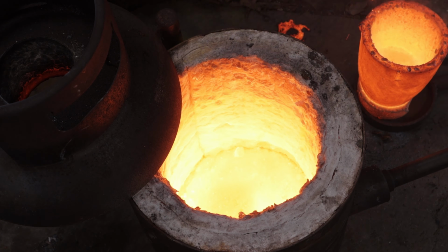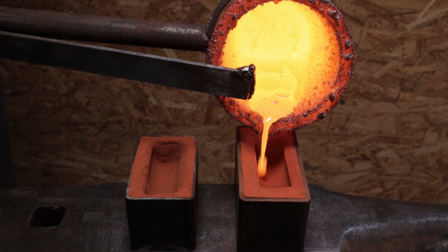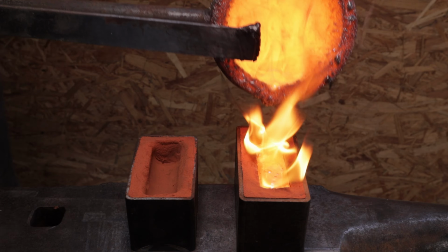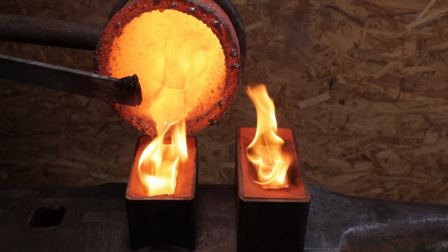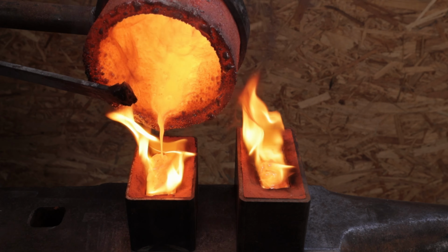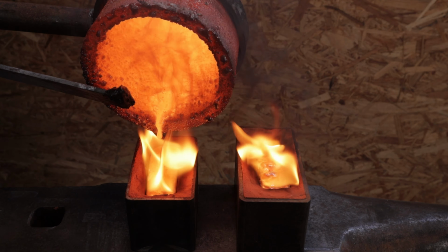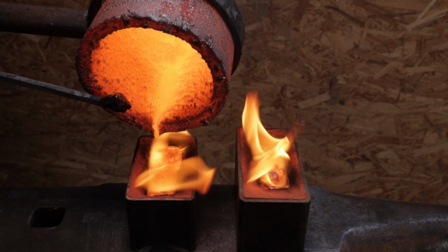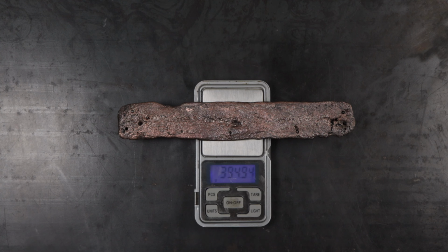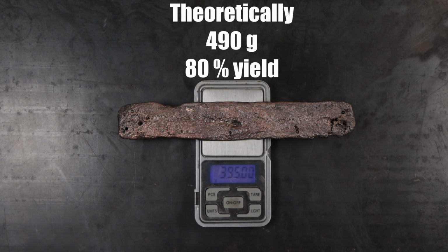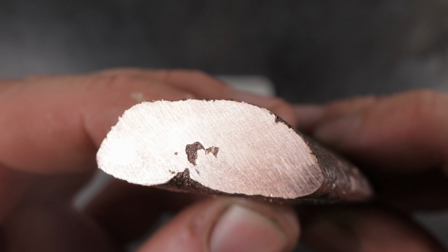I removed the slag and poured it into a sand mold. I did recast the ingot, because I probably got an admixture of copper metal and sulfide. The yield is only 80%, but I think that a part of the copper is trapped within the slag. The surface is porous, but it's actually compact.